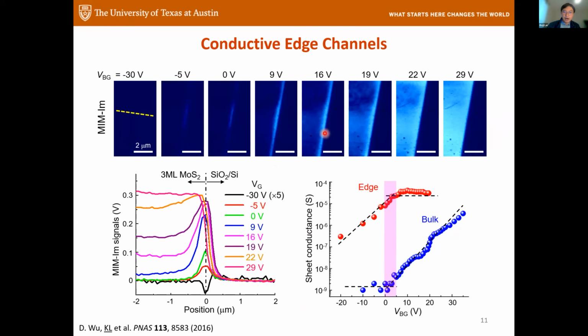Okay, so this is like a 2 monolayer, or 3 monolayer, 4 monolayer. You might ask, what happened for a monolayer, single layer? And the result is pretty much the same. The imaginary part increases monotonically, the real part increases and decreases. And before that, you get some kind of conductance near the edge.